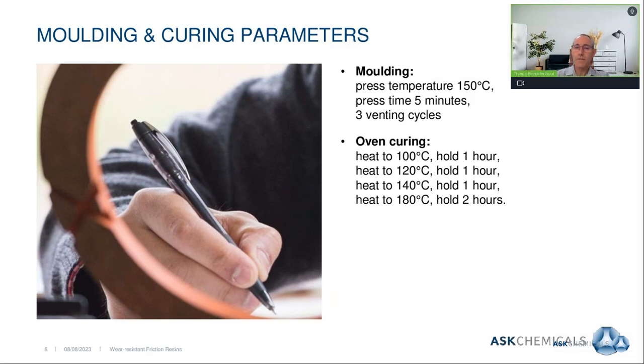We look at the hot press molding conditions and the oven post-curing conditions. In the case of the hot press, we have chosen a top and bottom platen temperature of 150 degrees Celsius, a total pressing time of 5 minutes, inclusive of 3 degassing cycles.